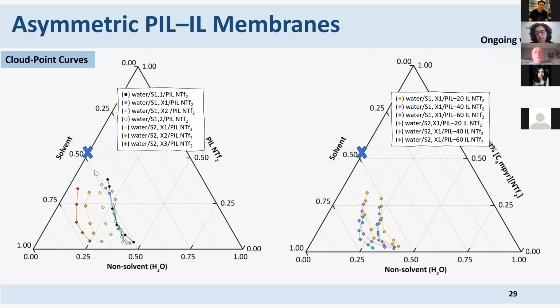And here it's, again, a ternary diagram, but this time for 20, 40, and 60% of ionic liquid. And we can see that all the phase diagrams become very close to each other. So when we put this membrane inside of the coagulation bath, we will have exactly this trajectory inside the two-phase region.